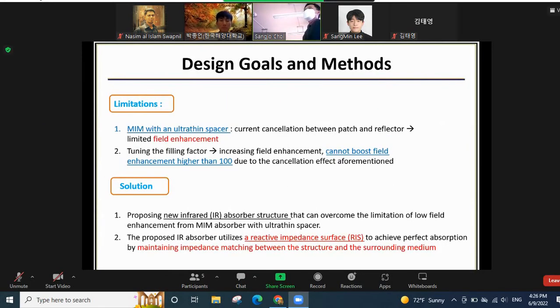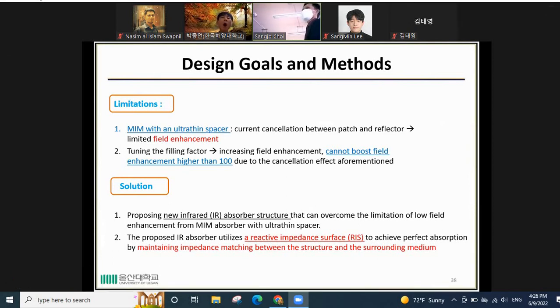So this structure also has a limitation with the ultra thin spacer, current cancellation between patch and reflector, and this creates limited field enhancement. And also tuning the filling factor increases field enhancement, but this structure cannot push field enhancement higher than 100 because of the cancellation effect. So for the solution of the problem, we try to design a new infrared absorber structure that can overcome the limitation of low field enhancement from the MIM absorber with ultra thin spacer. Our design is using a reactive impedance surface to achieve perfect absorption by maintaining impedance matching between the structure and the surrounding medium.